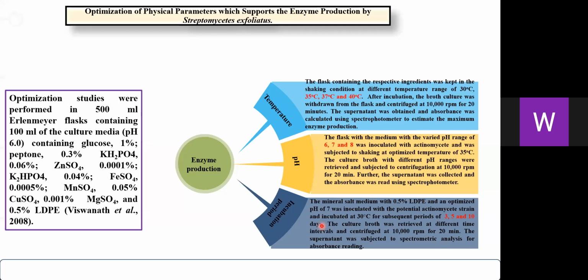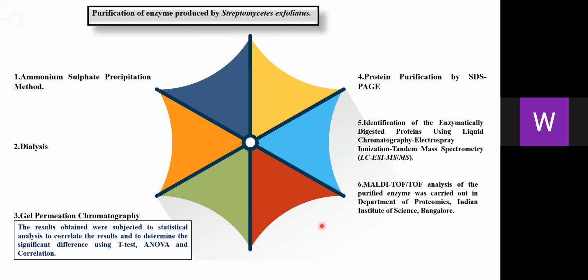Optimization of physical parameters to support enzyme production by Streptomyces exfoliatus. Optimization studies were done in order to find out the maximum enzyme production by Streptomyces exfoliatus. For this purpose, temperature, pH, and period of incubation were taken for the study. Temperature range of 30, 35, 37, and 40, pH of 6, 7, and 8, and incubation period of 3, 5, and 10 days were assessed and optimized by turbidometry method.